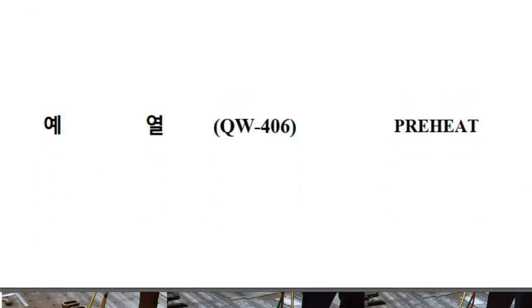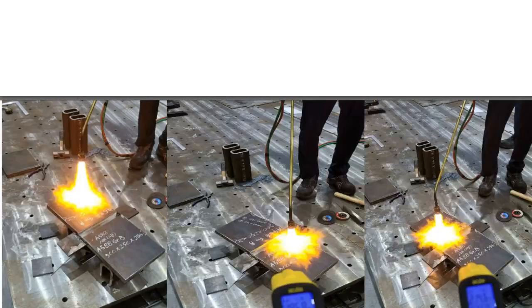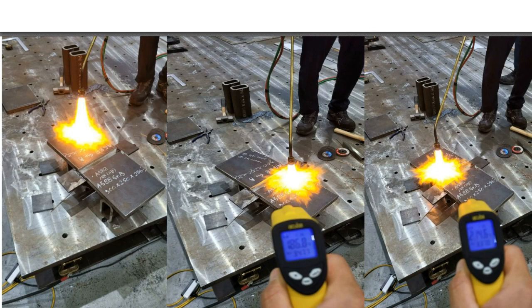And I'm going to introduce the preheat, because preheat is really important for ferritic steels. Here, torch heating for the PQ test. So this is the base material. Set them together with small gaps, like 1 or 2 millimeters, and then on the surface of the metal you apply direct heat. This is one of the methods of preheat.